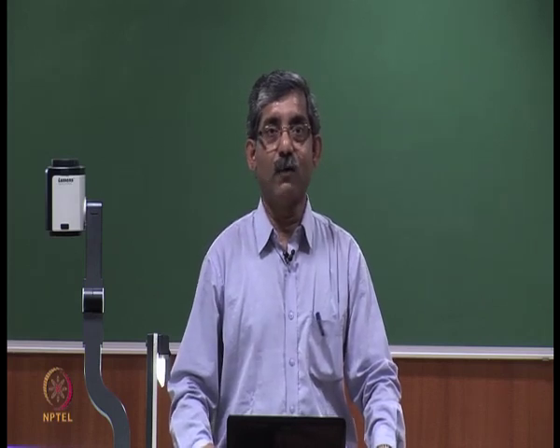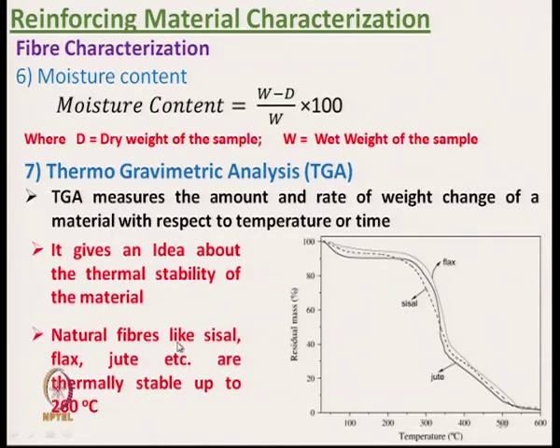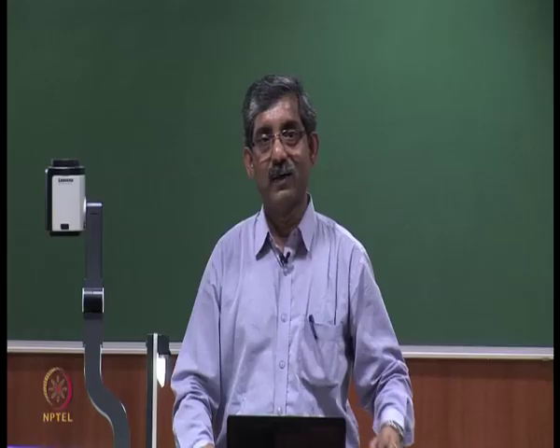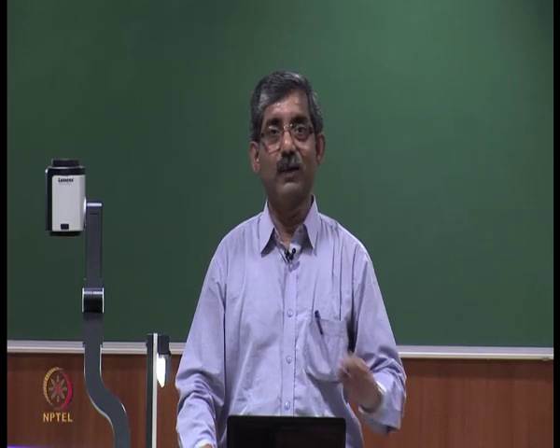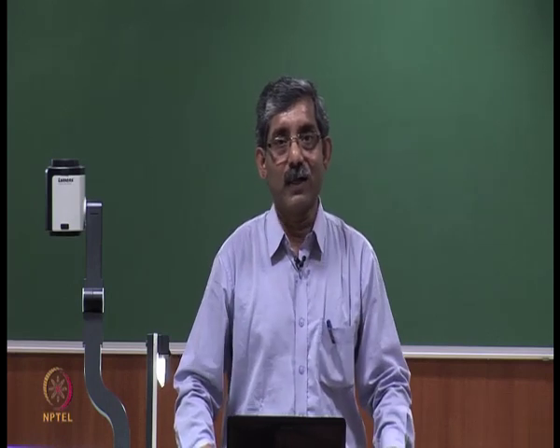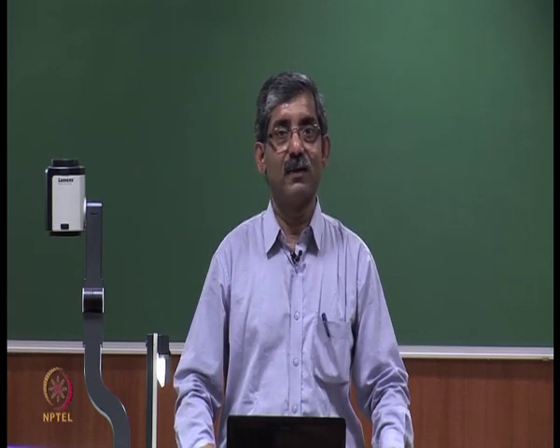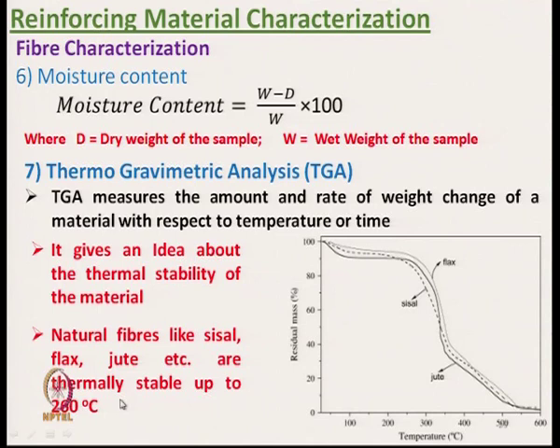It gives an idea about the thermal stability of the material. If the material is not stable, that means it will lose its weight, the residual mass will be less. Natural fibers like sisal, flax, jute etcetera are thermally stable at least up to 250 to 260 degree Celsius. So, these are three different natural fibers, and initially the residual mass is 100% and it maintains close to 100% at least up to 260 degree